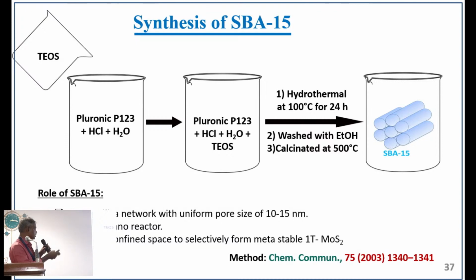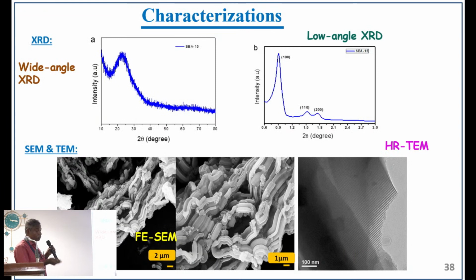So this produces a pore size of around 10 to 15 nanometers, and acts as a nanoreactor, and the 10 nanometer pores provide a confined space to grow our own MoS2 nanoparticles inside the material. So this is the characterization of the SBA-15 we prepared. We need to confirm whether the material is obtained or not. The wide angle shows a peak around 25 degrees for the amorphous silica, and the low angle peaks at 100, 110, 200 are perfectly reproduced for the same material. The SEM and TEM analysis shows that the material has very good morphology as well as very good purity, because the nanochannels should be completely free from the surfactant materials. So we got completely pure SBA-15 using this method.